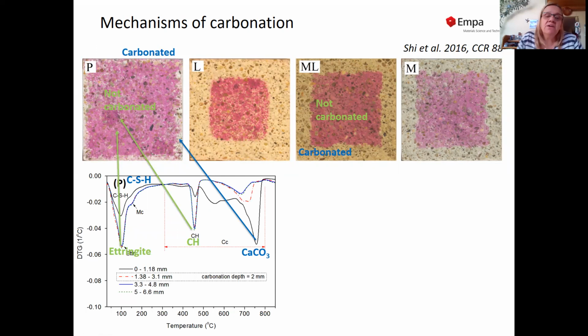We can also measure TGA on slices of this carbonated cement. And we can see, if we start in the center, the not carbonated part, we have a lot of portlandite. We also see ettringite and CSH as a broad hump. If we go nearer to the surface, we see a decrease of portlandite, here down to the black line, and the formation of additional calcium carbonate. We also see a decrease in the amount of AFT and AFM phases and possibly of CSH.